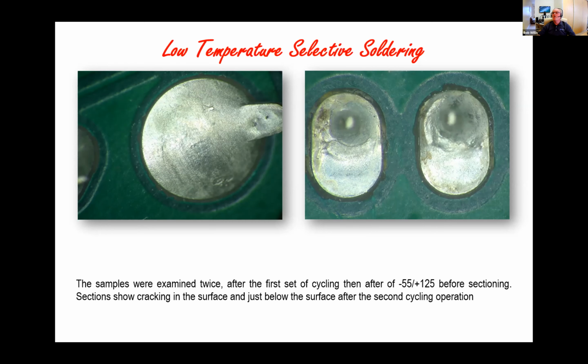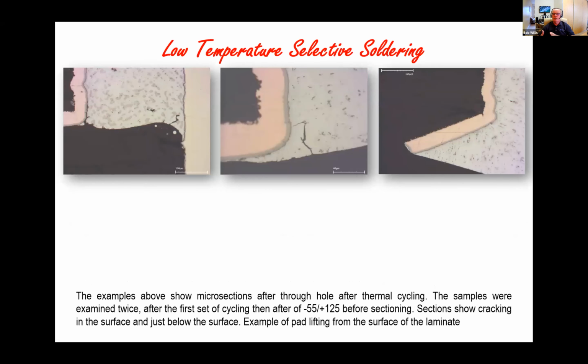Through-hole joints very rarely ever fail in the real world of manufacture and in the field, I would hasten to say. But you will see changes. And I was able to see changes in the joints after temperature cycling, which did show some cracking. And you can see in these microsections, the first and second from the left to the middle of cracking.